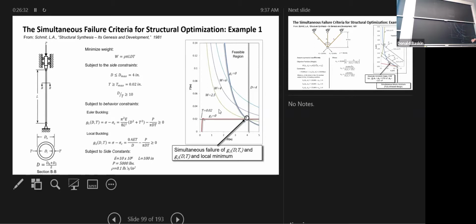See that? Right? And then there's the local buckling. The local buckling is a little bit less useful. It kind of goes like this. It's this line right here. Okay. So knowing that you're getting lighter as you go in this direction, you're picking D's and T's to get you going this way. This tells you that the lightest possible solution is actually right here. So actually, I've drawn that a little bit high. It's meant to be on the 0.02 line. So that is the lowest weight solution because it's at the lowest contour line that meets all those constraints: constraints for the diameter, constraints for the thickness, constraints for local buckling and global buckling.